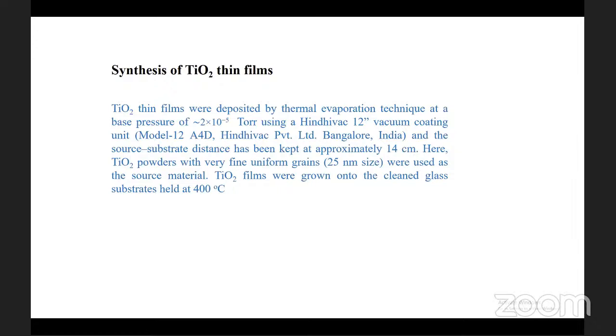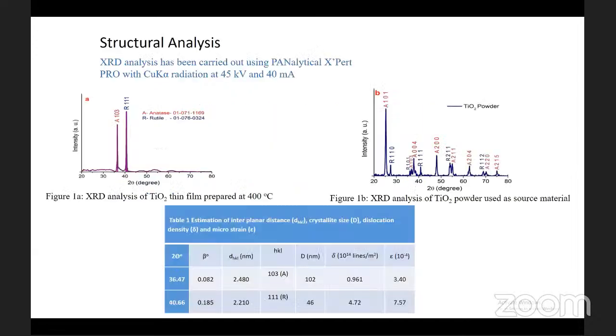TiO2 thin films were deposited by thermal evaporation technique at 400 degrees centigrade using a high vacuum coating unit at around 2 times 10 power minus 5 Torr base pressure. The source to substrate distance has been kept at approximately 14 centimeters. Here, TiO2 powder with very fine uniform grains, 25 nanometer in size, was used as the source material.